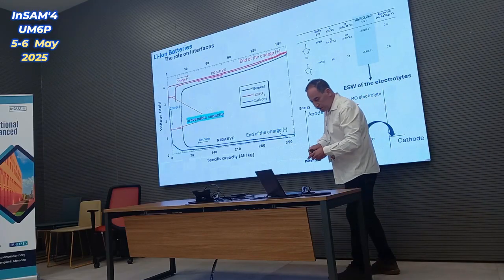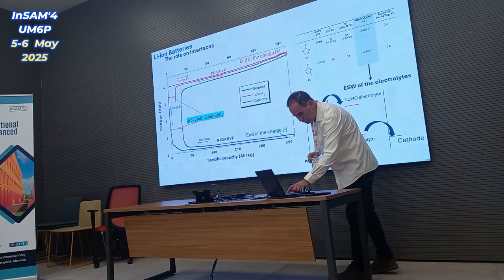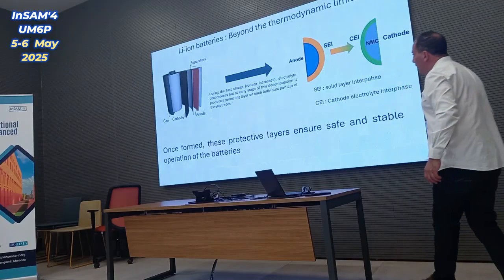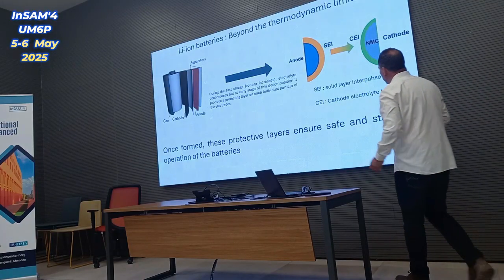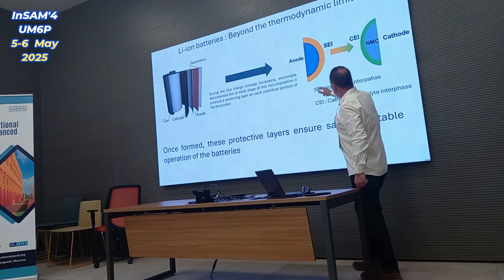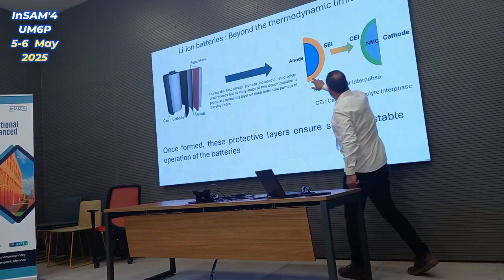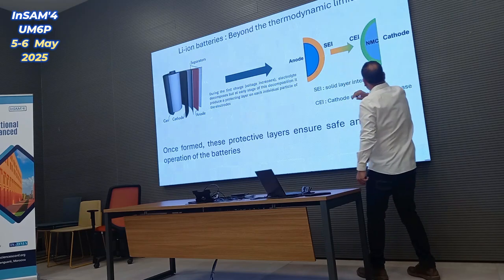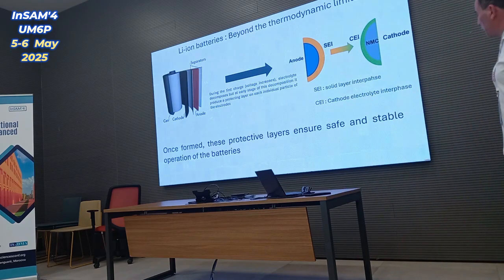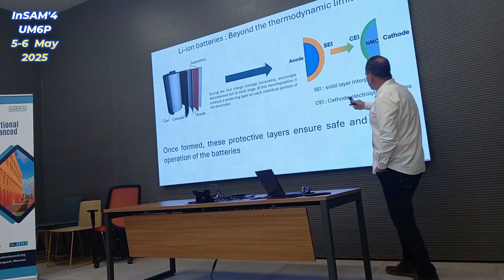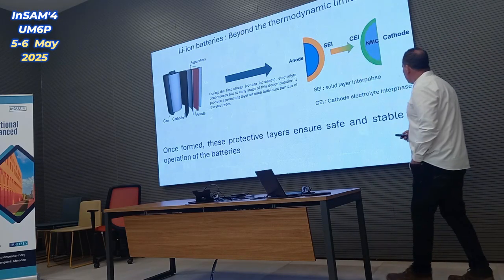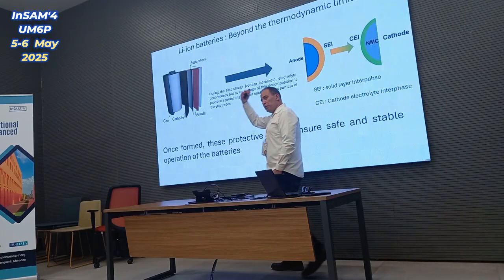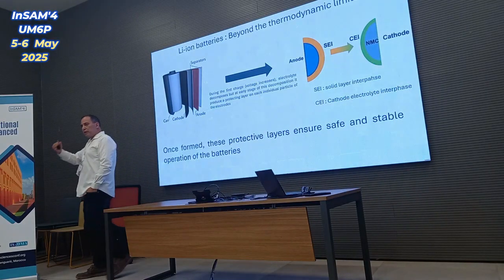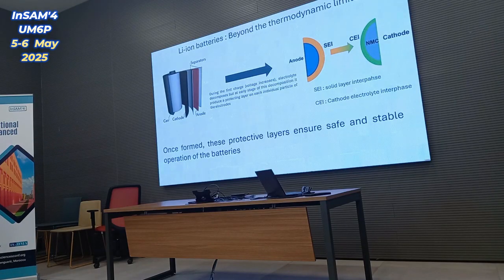And this reaction is not useful for storage, because it is irreversible. But at least for those reactions, the product of this reaction will provide a coating of the anode material, the negative electrode, and of the positive electrode. And this coating is what we call the passivation layer. On the anode side, we call it the solid electrolyte interface, and on the cathode side, the cathode electrolyte interface. And once it's formed, it will stop the direct contact between the electrolyte and the cathode material and the anode material. Then the irreversible reaction will stop.